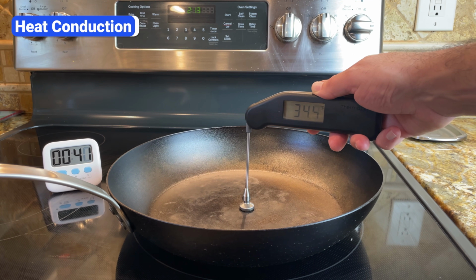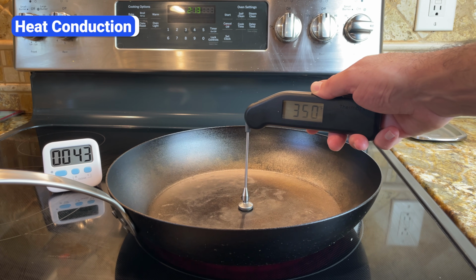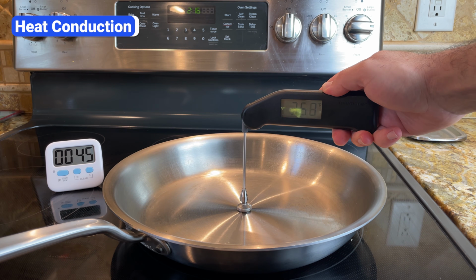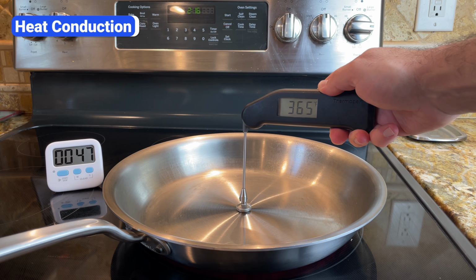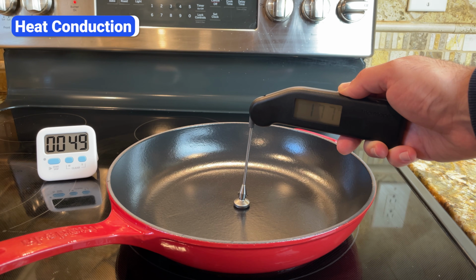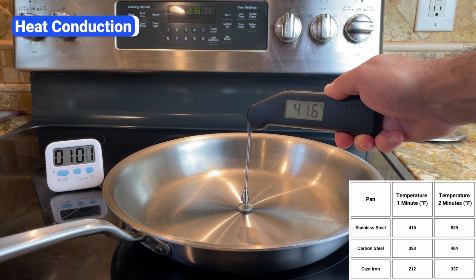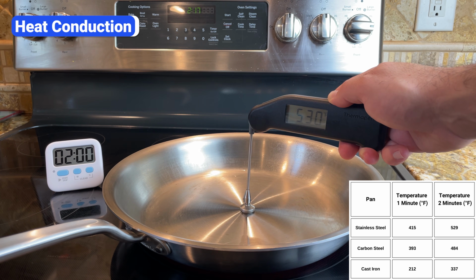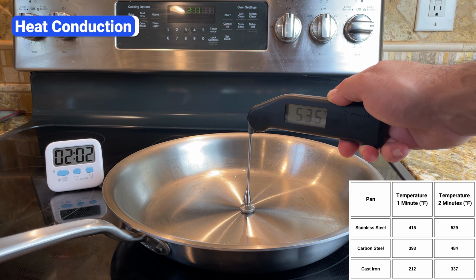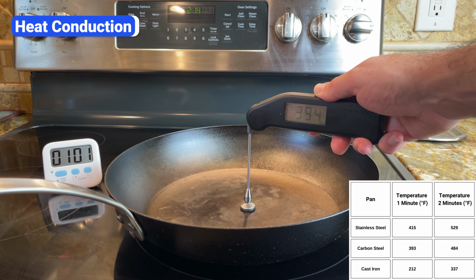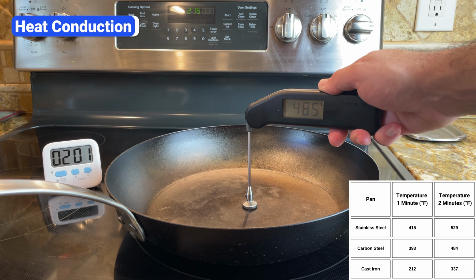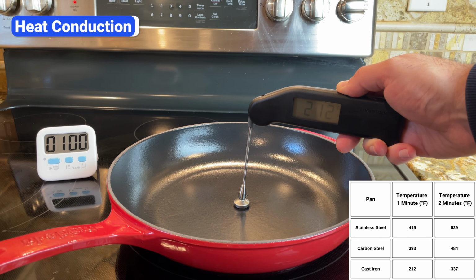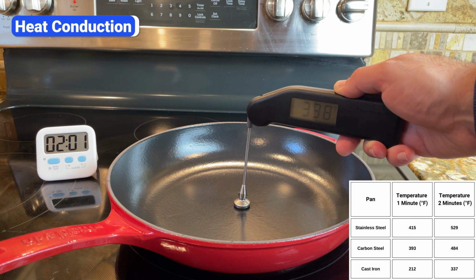To test how quickly these pans heat up, I placed them on the same burner at the same temperature and measured each pan's surface temperature after exactly 1 and 2 minutes. The stainless steel pan heated the fastest, which wasn't surprising since its core layers are aluminum and aluminum conducts heat fast. Thanks to its relatively thin construction, the carbon steel pan wasn't far behind. And not surprisingly, cast iron heated the slowest.